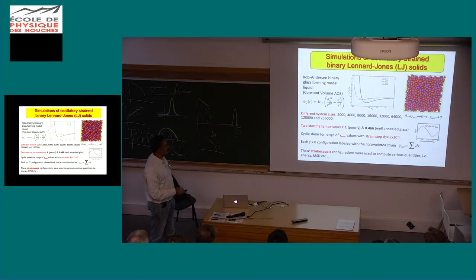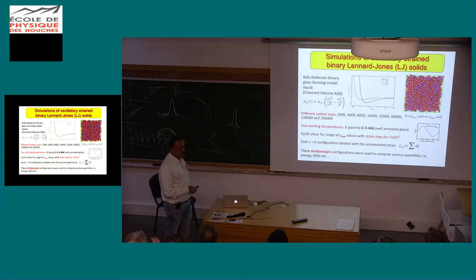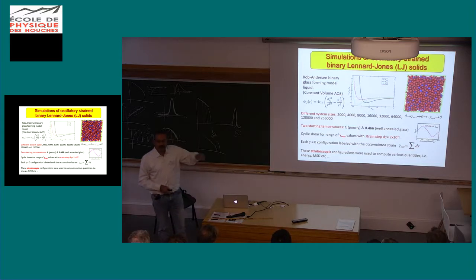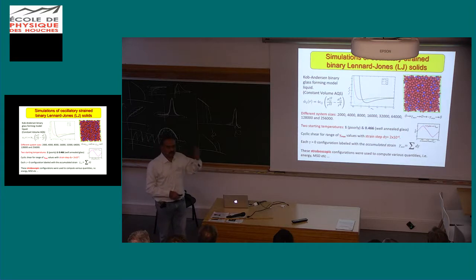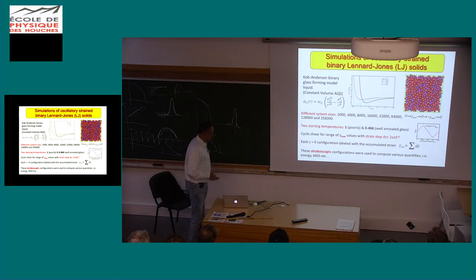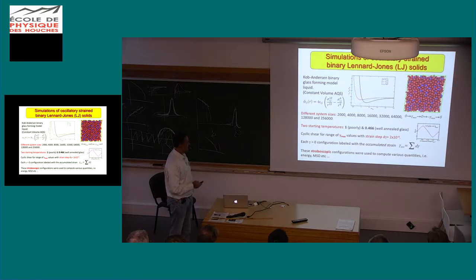Now, we look at the configurations typically at the end of each cycle. So that's what gamma equal to 0 means. But as the number of cycles increases, what we call the accumulated strain, which is the total strain through the cycle times the number of cycles, increases, and this is kept track of. It's called the accumulated strain. And like I said, we typically look at stroboscopic configurations, that is at the end of each cycle.